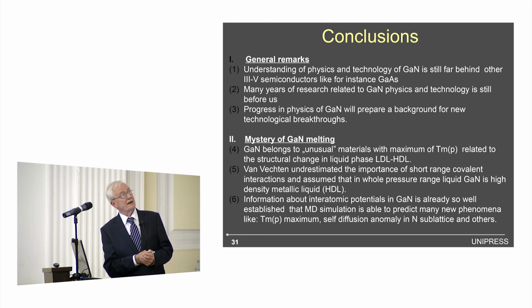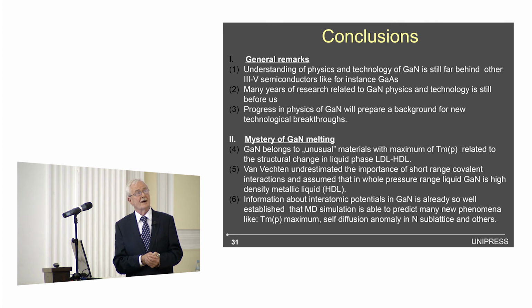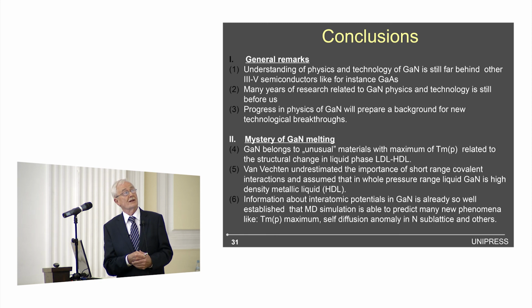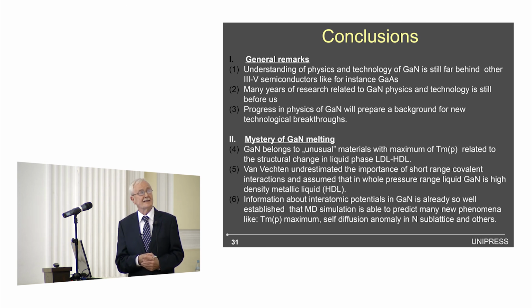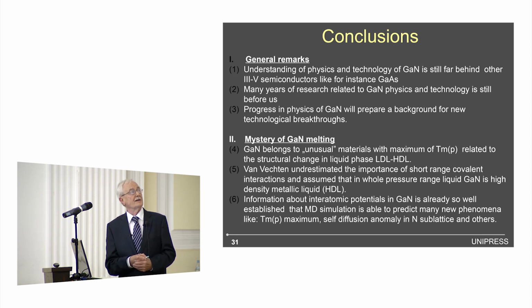And the mystery of GaN melting, the conclusions are the following: GaN belongs to these unusual materials with a maximum in the pressure dependence of melting temperature. And it is related to the structural change in the liquid phase from low density liquid to high density liquid. The other conclusion is that Van Vechten really underestimated the importance of short-range covalent interaction, and assumed that in the whole pressure range, liquid GaN is a high-density metallic liquid. And it seems that this was the mistake which he made.